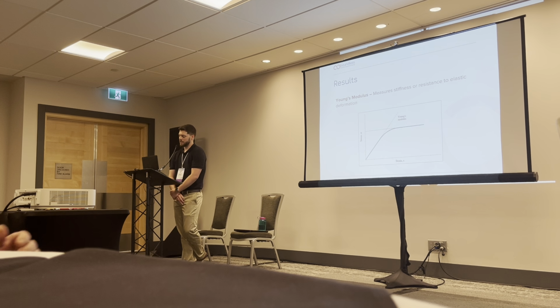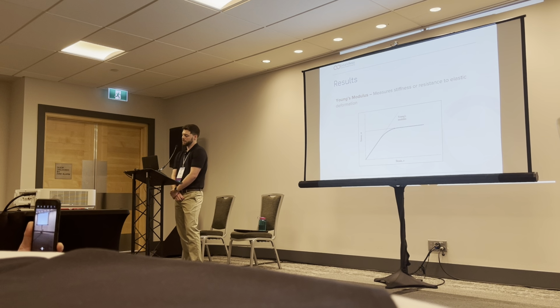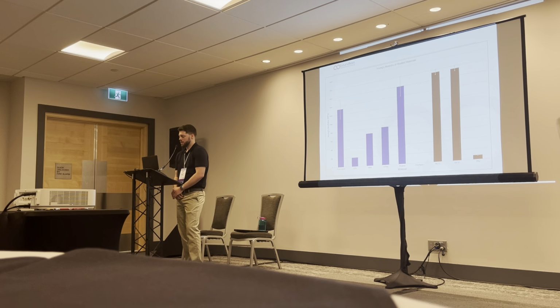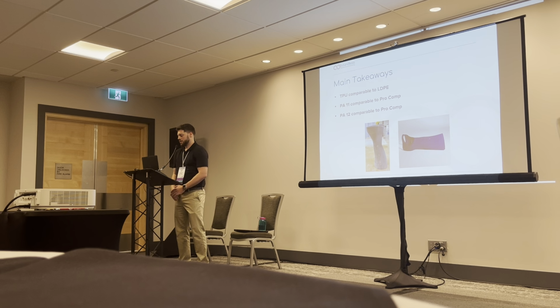The last property we looked at is Young's modulus, or the stiffness of a material, and that's represented by the stress-strain relationship of a tensile test. So stiffness of the material, we found PA11 and PA12 were very similar to a ProComp, and again, TPU very similar to a low-density polyethylene. So main takeaways, we found that TPU was very comparable to a low-density polyethylene in the categories that we evaluated. However, it is a little bit heavier and not quite as stiff as the low-density polyethylene.